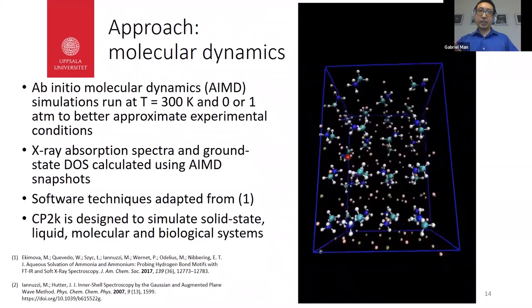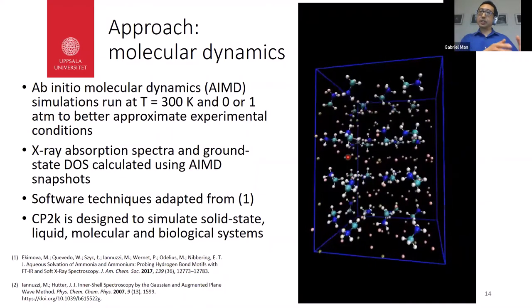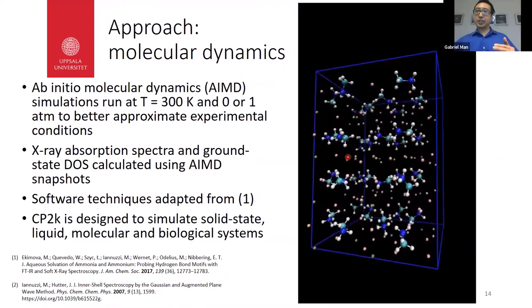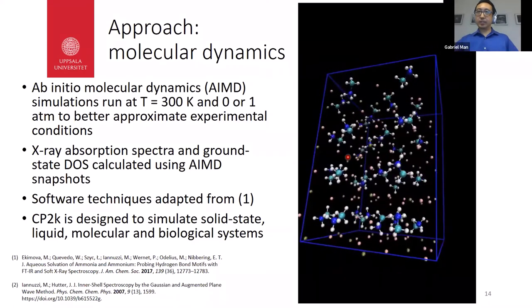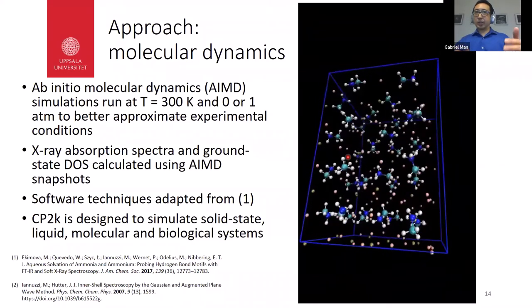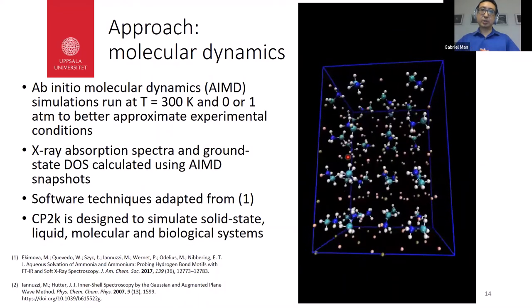And so they simulate. So what they do is they have a starting crystal structure. And then they run a simulation with the temperature set at 300 Kelvin and the pressure set at either 0 or 1 atmosphere to try to simulate the experimental conditions more accurately. And so they complete a simulation, they take a variety of snapshots, and then they calculate the X-ray absorption spectrum for each individual atom, and then generate an aggregate spectrum for comparison to experiment. So the toolkit they use is CP2K, which is designed to simulate solid state, liquid, molecular, and biological systems.